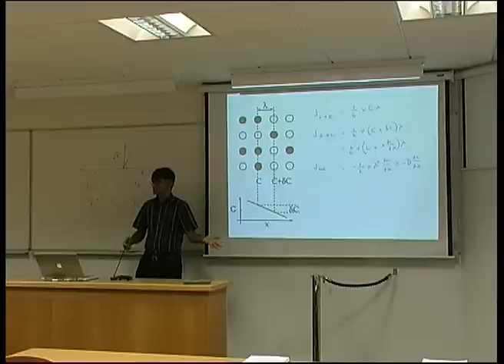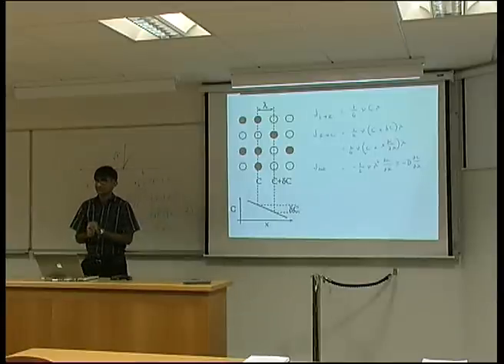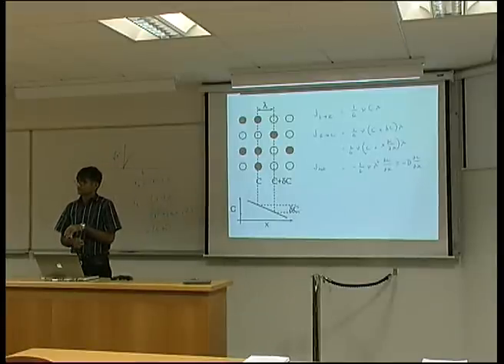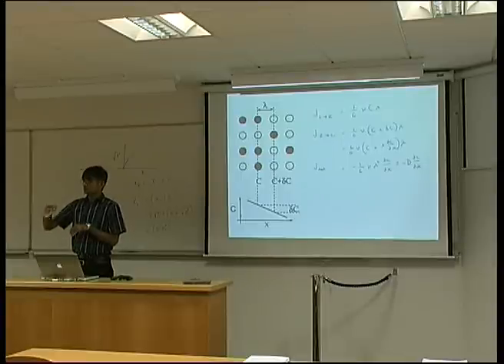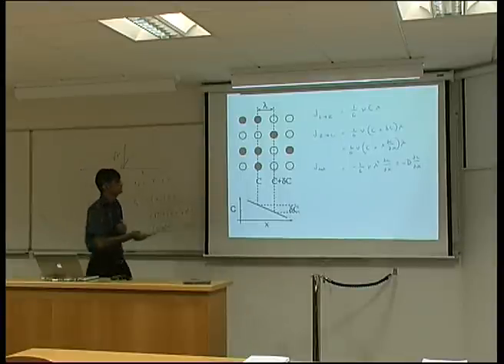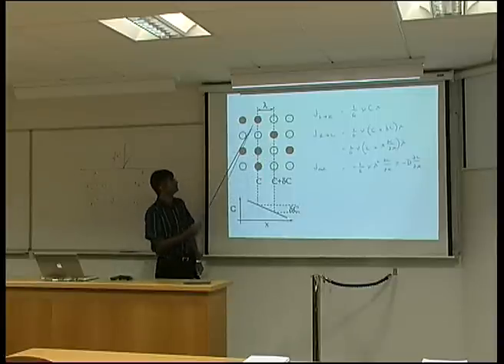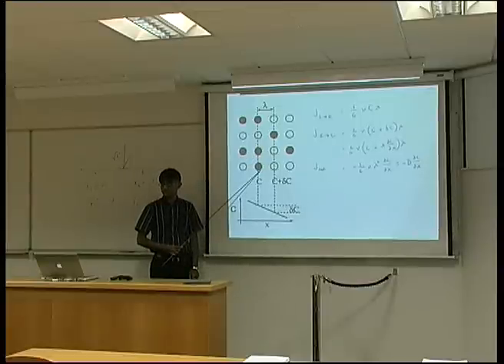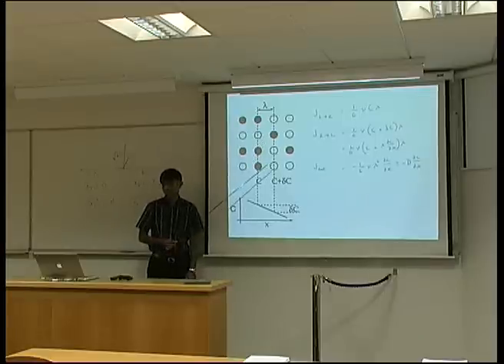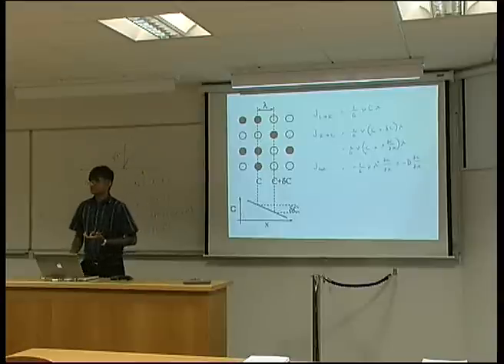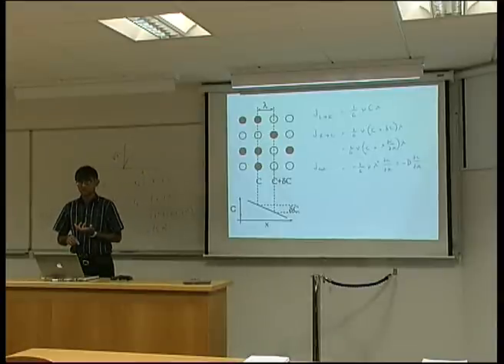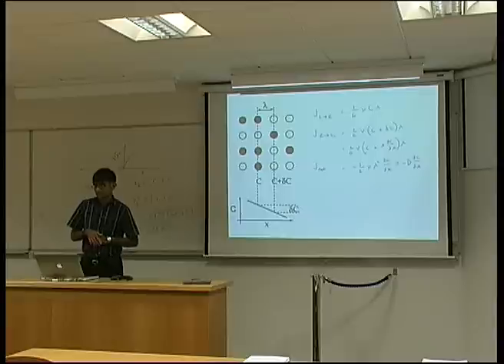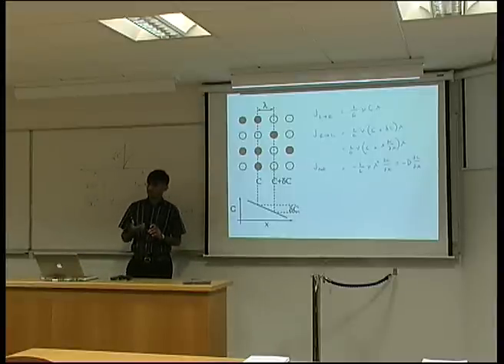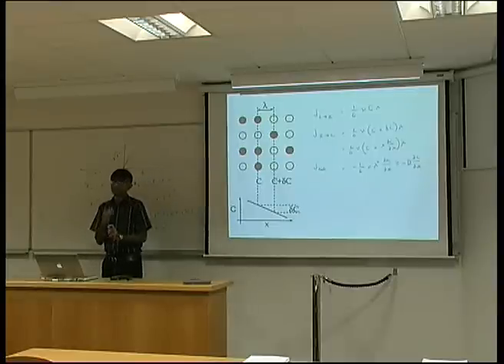Now, what is the key assumption here in deriving these equations? That everything depends on concentration gradient. Yeah, because we've simply said that the probability of jumps in this direction will be proportional to the number of solute atoms here, and similarly the jumps in this direction will be proportional to the number of solute atoms there. So the key assumption is that the flux is proportional to the concentration gradient, and we haven't actually justified that in any way. It seems intuitively correct, but we haven't justified it. By the end of this lecture you'll see a different interpretation.